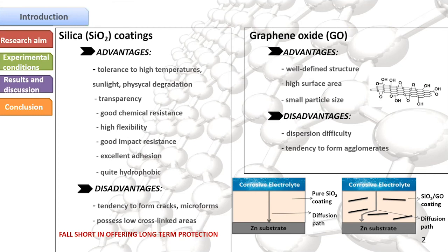and disadvantages. Silica coatings are widely used on metals to mitigate corrosion because of their extraordinary tolerance to high temperatures, sunlight, and physical degradation. It has advantages such as transparency, good chemical resistance, high flexibility, and good impact resistance. And we know that the siloxane groups of silane molecules form strong covalent bonds with the substrate, generating excellent adhesion among the zinc surface and the silica coating.